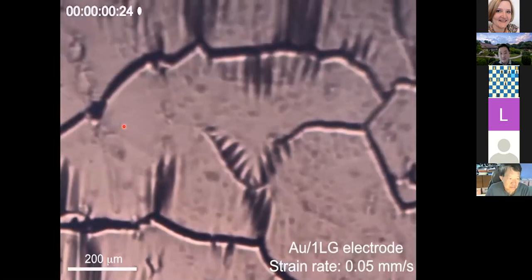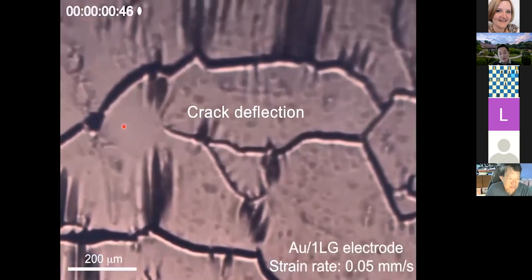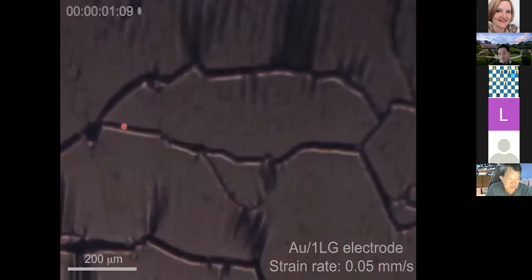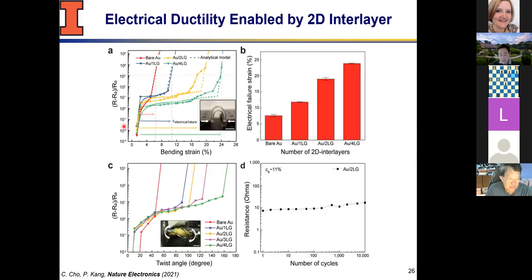It's something that's still quite interesting to us, but here's just how the cracks are. This is, I believe, the real time that you're seeing. At a particular strain and increasing strain, you see that these cracks are interacting and then they propagate. I don't have the video for straight crack propagation. For that, it's just a straight crack. There's really never any interaction and then any further gold patches, kind of bridging effect that can be seen.